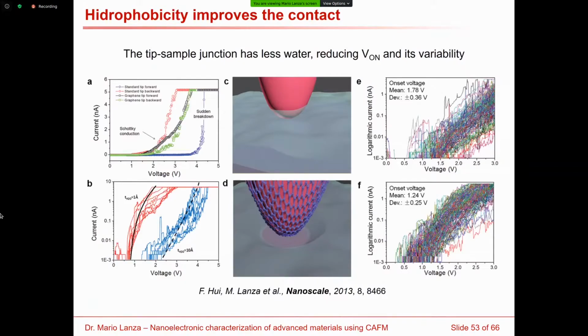This conclusion was extracted by measuring IV curves with both tips. And as you can see here in panel A, with the normal tip measuring on silicon, we observe that the shape of the forward IV curve, which is the blue, shows a sudden breakdown, a sudden current increase, which looks like a breakdown of a dielectric, and there is a shift towards lower potentials in the backward curve, which is the red.